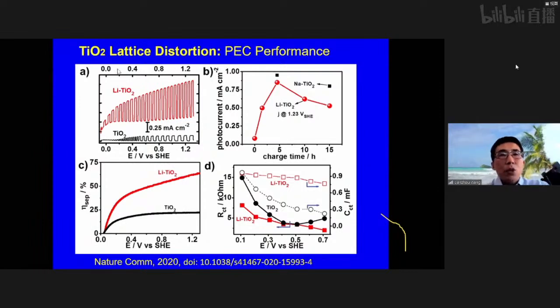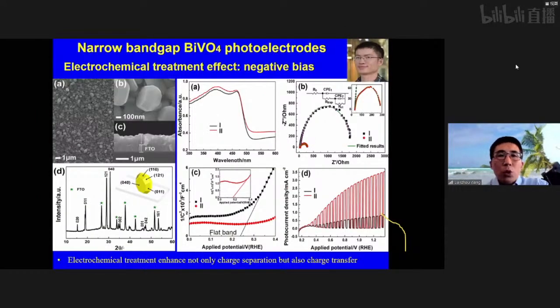But as I said, TiO2 still has a very wide band gap, and basically it cannot reach very high PEC water splitting performance. So we also turned our attention to some narrow band gap materials. In this case, it's a bismuth vanadium oxide photoelectrode, and we use a similar approach, hydrothermal treatment, to prepare the electrode. We applied a very small negative bias to the system for only around 2 or 3 minutes, but we found quite an interesting phenomenon.